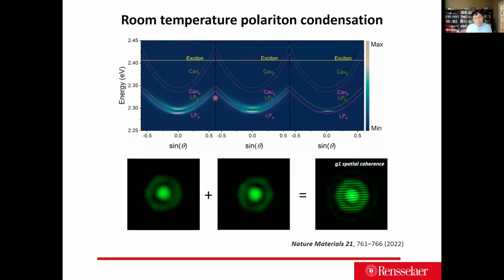As you can see there, we have a little bit of optical birefringence due to the orthorhombic phase of the cesium lead bromide. Essentially, in plane, you have two indices. Those are birefringent crystals, but they can still condense at the lower polariton level, and you see nice G1 coherency. You take one condensate image and another condensate image, flip them and do the interference. The left side and the right side show coherency built up across the whole condensate.